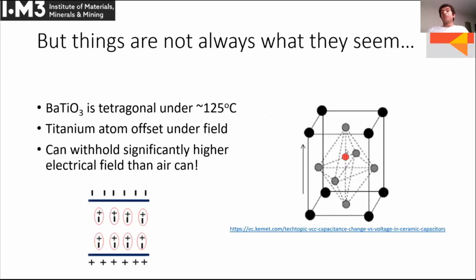So in the previous slide, I showed you barium titanate was cubic. That's only true above 125. So there's more problems. I keep solving problems, but we face some more. Under 125, it's tetragonal, which just means that one of the axes is longer than the other 2. In this case, it's the vertical. So because the axis is elongated, the titanium atom in the middle can offset when it's put under a field, so it has a positive charge. And so once we start putting it between the positive and the negative plate, that titanium atom really wants to attract to the negative plate. And that's what I've got on the left bottom image here.